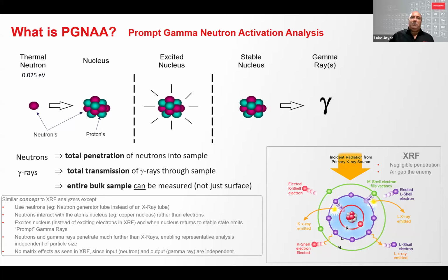It's a similar concept to another more familiar technique to some, XRF or X-ray fluorescence, which uses X-rays to interact with the electrons surrounding the nucleus, exciting the atom by knocking out an electron from a lower energy shell, which results in a high energy shell electron filling that vacancy and emitting the excess energy as a characteristic X-ray.